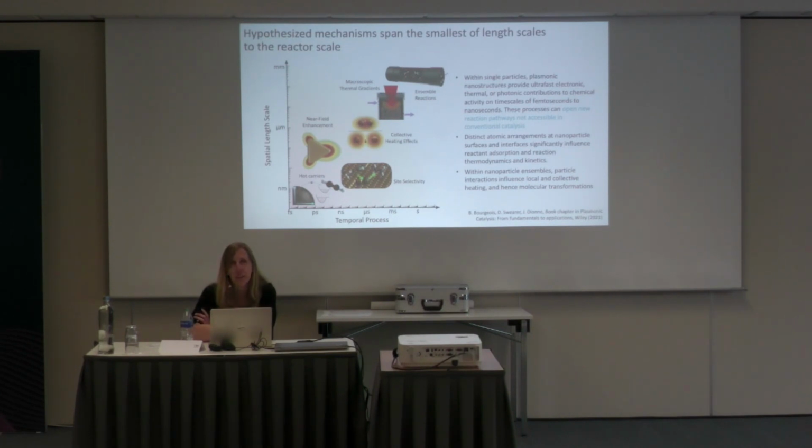For the ammonia production, it's so low in part because those were results at room temperature and pressure with just 100 milliwatt lasers. So if you compare room temperature and pressure and only getting below 1% for ammonia, it's a really promising start when normally you need to be at 200 megapascals and like 500 degrees C. So we certainly could have turned the temperature up a bit or the pressure up a bit and probably gotten higher yields, but I think there's a lot more room to play around with the particular nanoparticle, like phase, geometry, composition, etc. Thank you.